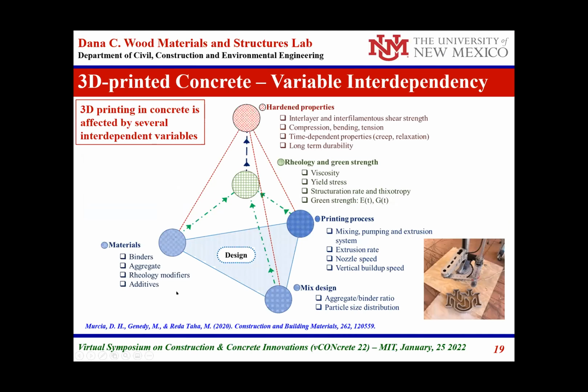We've done some work trying to identify the factors affecting 3D printing of concrete, and of course rheology and green strength of concrete is at the heart of this. So we developed what we call a tetrahedral-like model, similar to the silica model, where the 3 points in the base are basically the materials used, including binders, aggregate, and rheology modifiers and additives, the mix design being used, and the printing process that is used. And this all comes together to affect the rheology and green strength of the material.